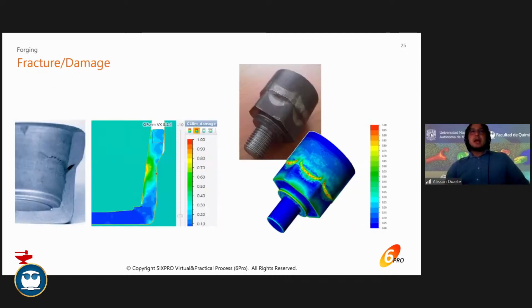So that's it here. For example, you can check also cracks. It's different from folds. Folds or laps is when the material goes against itself. But in this case, there is actually a crack. So this material tries to come here. There is this tensile stresses, and actually you want to separate material. So here you have a crack. I said a fold is like a crack, but here you have a crack. And the